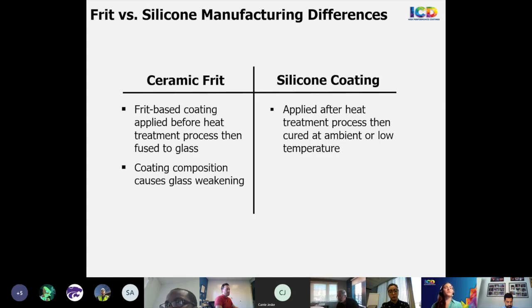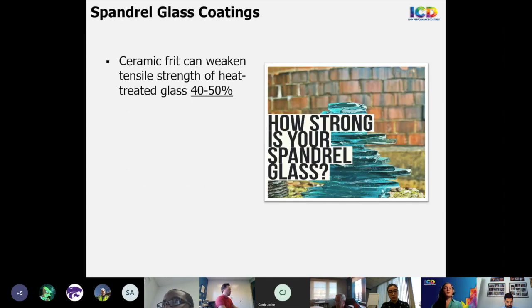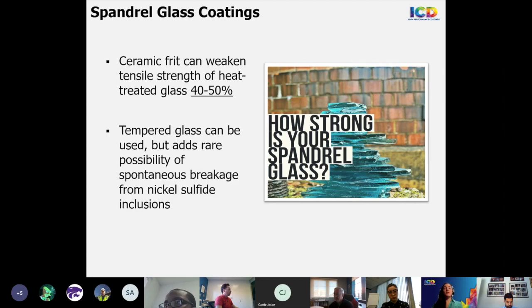The coating composition of frit can cause glass to weaken, and the natural bond of silicone does not weaken glass. So we saw that studies have shown that frit can weaken the tensile strength of heat-treated glass by about 40 to 50%. Tempered glass can be used to mitigate that risk. As Kayla mentioned, there are some other risks associated with tempered glass. It is very rare, but it does happen.